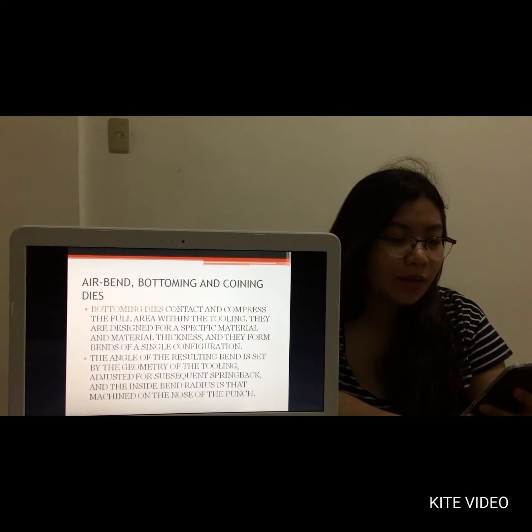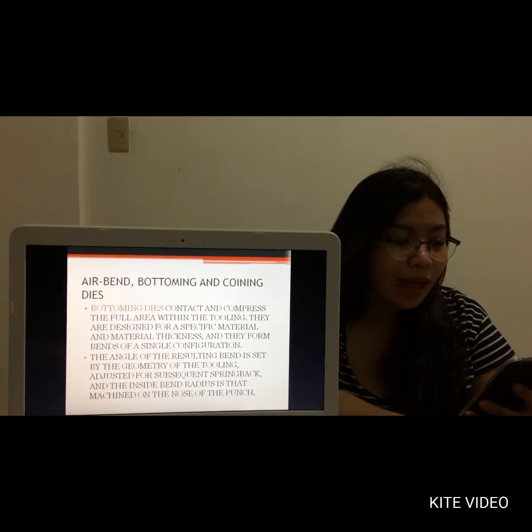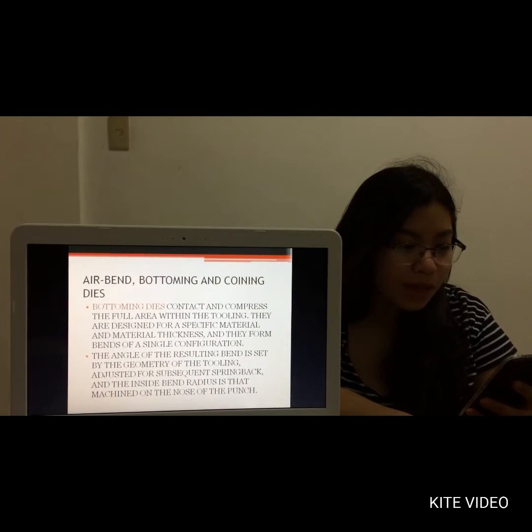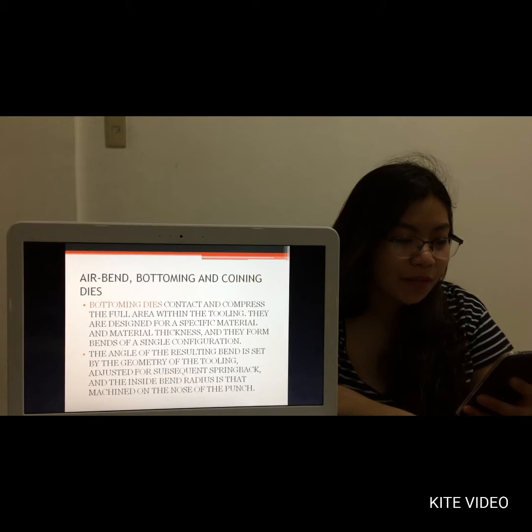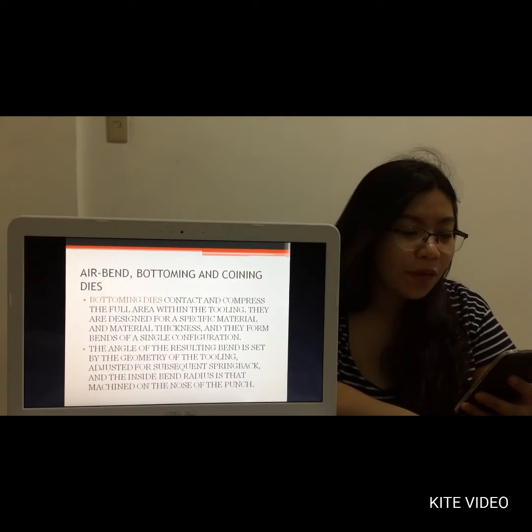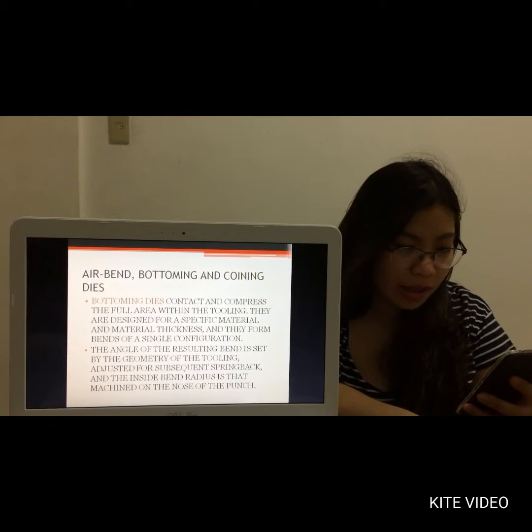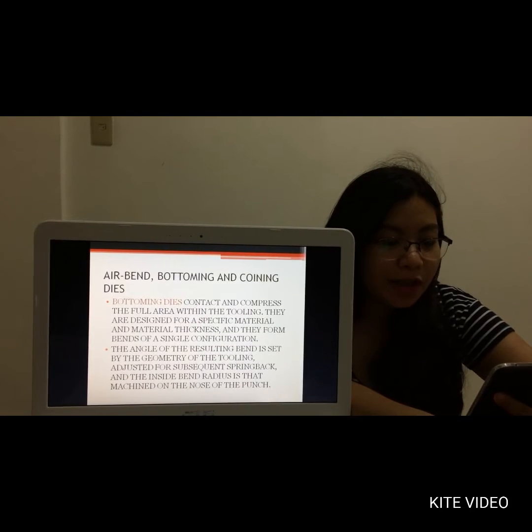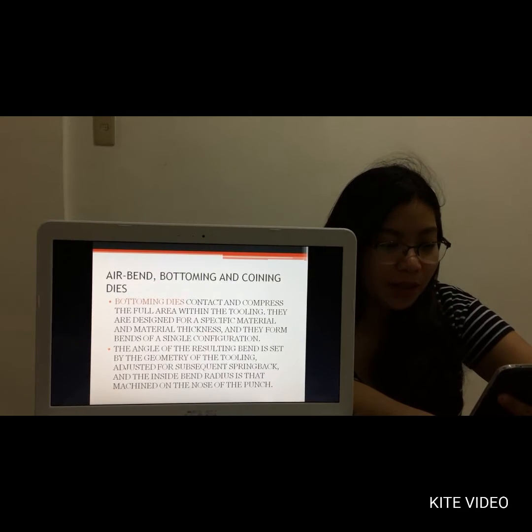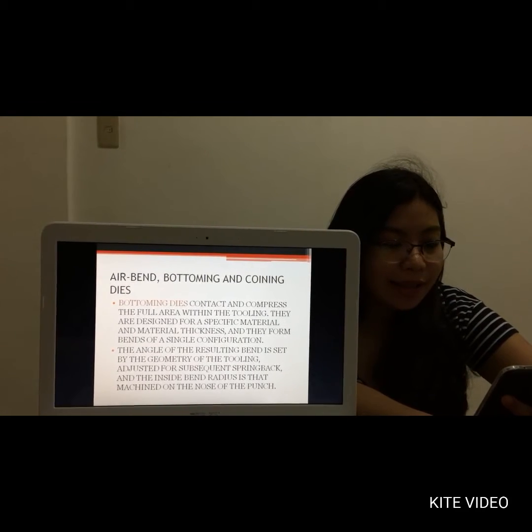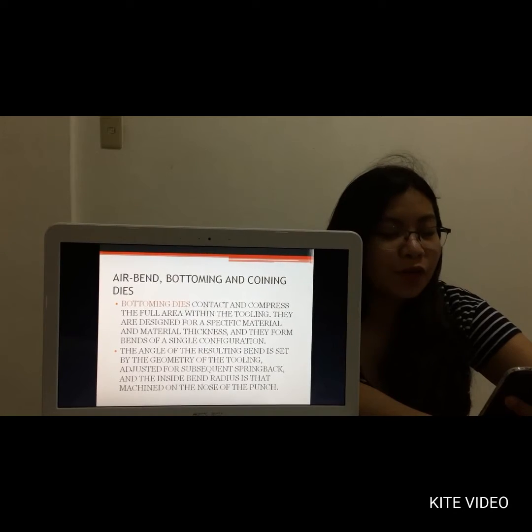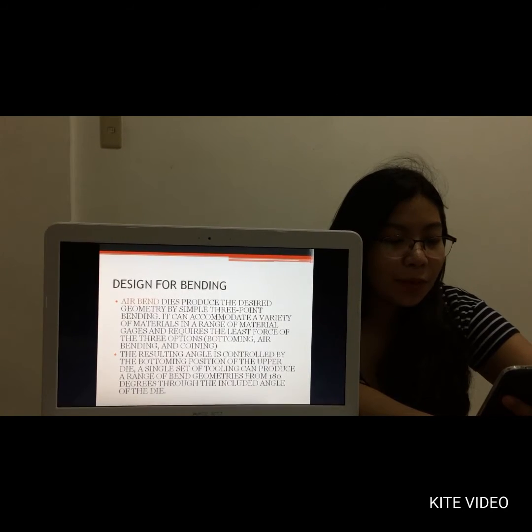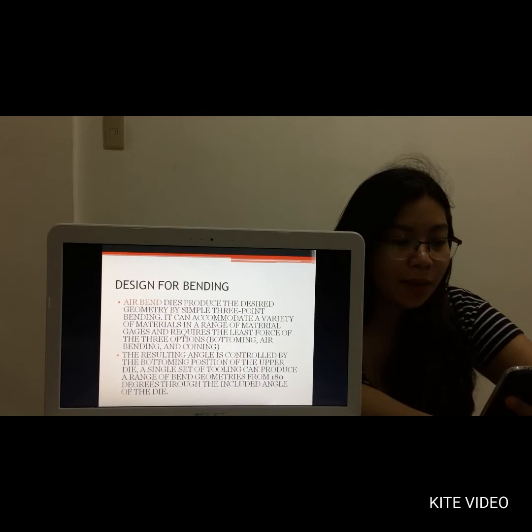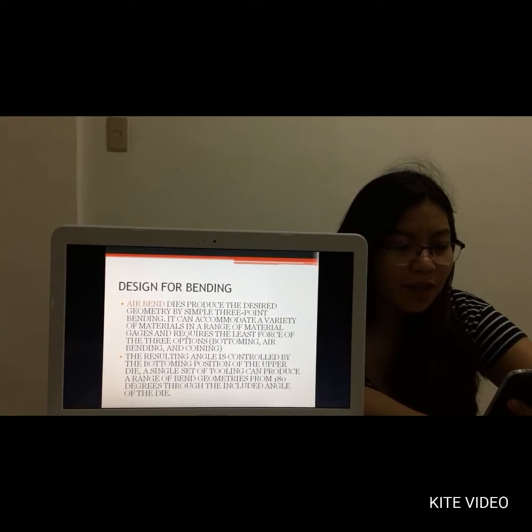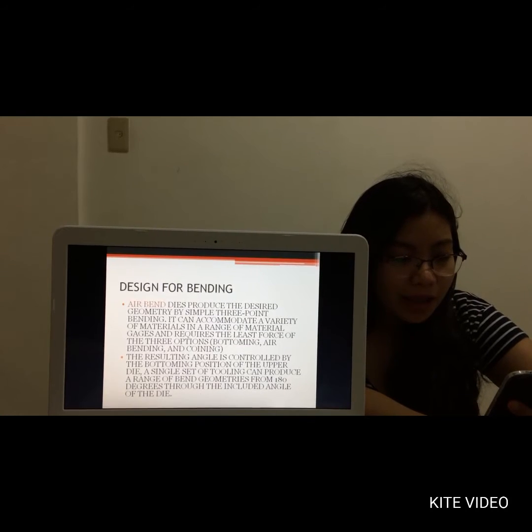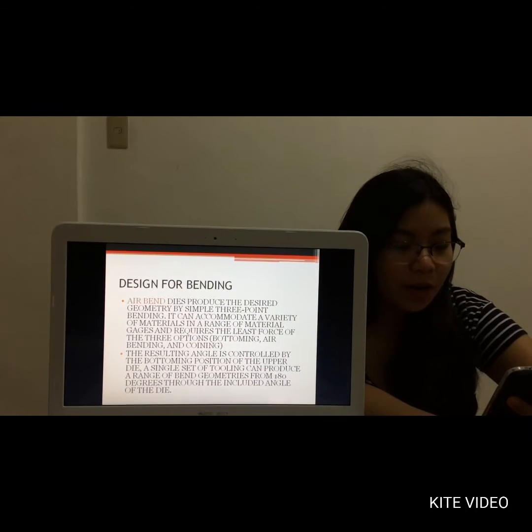Air bend, bottoming, and coining dies. Bottoming dies contact and compress the full area within the tooling. They are designed for a specific material and material thickness, and they form bends of a single configuration. The angle of the resulting bend is set by the geometry of the tooling, adjusted for subsequent springback, and the inside bend radius is that machined on the nose of the punch. Air bend dies produce the desired geometry by simple 3-point bending. They can accommodate a variety of materials in a range of material gauges and require the least force of the 3 options.